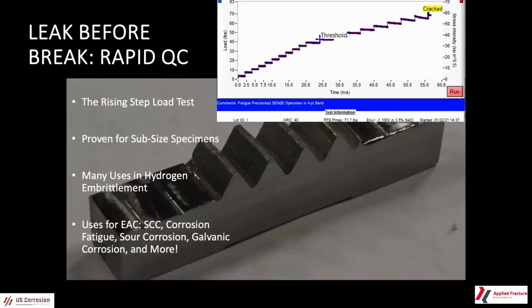So this is an example of the step loading test. This is one that we use a lot, and I personally like it because it's been proven to work really well to correlate between small samples as well as with full-scale samples. And it has a lot of different uses in hydrogen embrittlement. You can use it for quality control testing. You can use it for initial characterization and comparison of alloys. We also use it for failure analysis and forensic investigations.